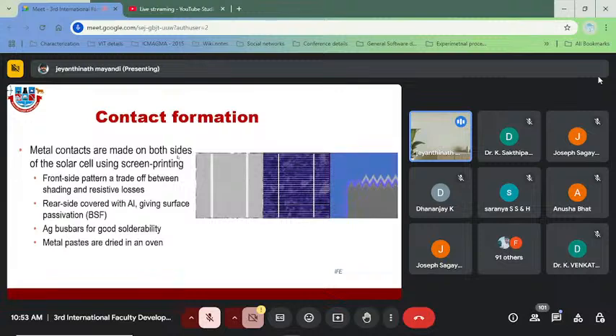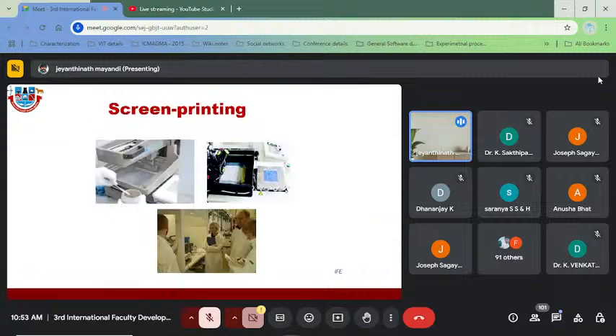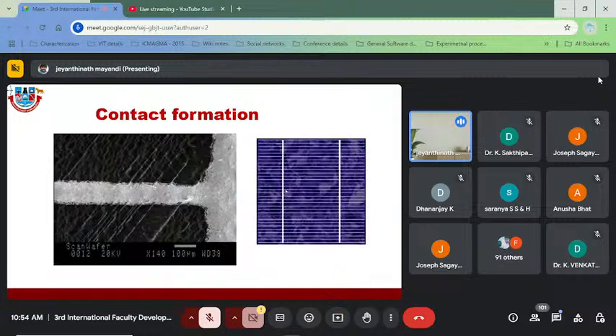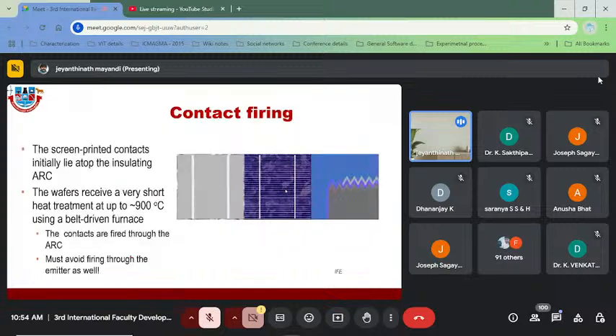Once the passivation is made, you can make contacts on the solar cell. The top is where you have coated the silicon nitride, while on the back side aluminum is coated, and the bus bars will be made from silver. On the front side all the contacts will be established with silver. This is done by screen printing, a very old method of squeezing silver paste onto the surface, and the printed electrodes have to be fired through the silicon nitride layer so that they can establish contact with the silicon. You can see closely in the SEM images how it looks.